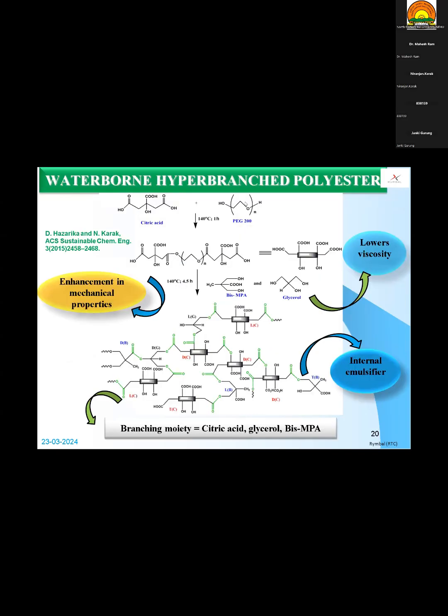Thus, in our research, we have produced the bio-based hyperbranched waterborne polyester system, where we use citric acid and glycerol as the bio-based system, and without using any external emulsifying agent, neutralizing agent, or catalyst, we have ended up with a beautiful environmentally friendly polyester system which can be produced from bio-based raw materials.